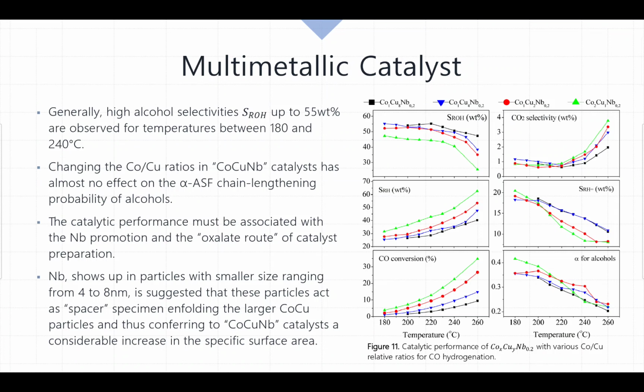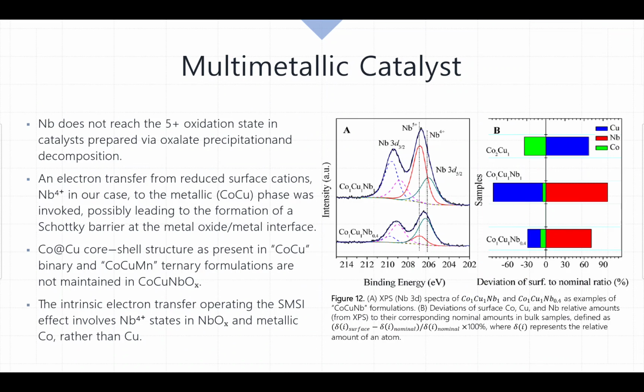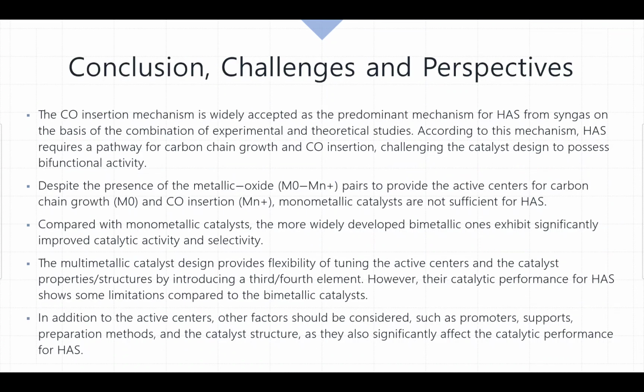CO conversion with all cobalt-copper based catalysts under low temperature reaction conditions remains below 20%. While it may seem appropriate to develop catalyst formulations providing higher activities, one has to keep in mind the considerable exothermicity of the process and the need to develop suitable means for managing the heat removal from the reactor. While some progress has been made, a number of challenges still need to be overcome to further advance the direct synthesis of higher alcohols from syngas.